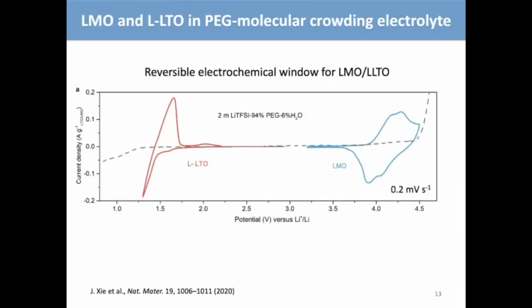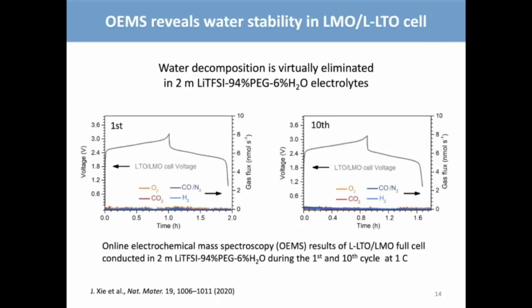So using this electrolyte from 4.5 volts all the way to 1.3 volts, we are able to apply LMO as a positive electrode and LTO as the negative electrode to see a full cell reaction in this electrolyte. So before we cycle the battery, we want to see whether the hydrogen evolution reaction or even oxygen evolution reaction is really suppressed in the full cell.